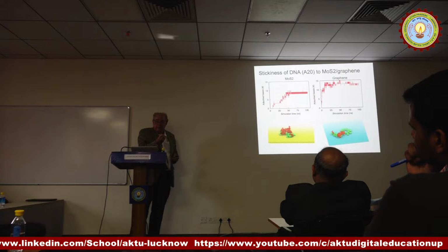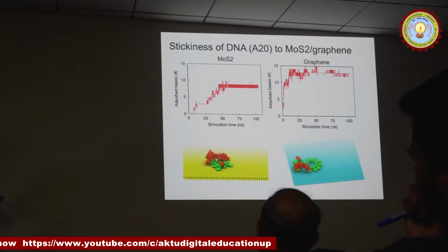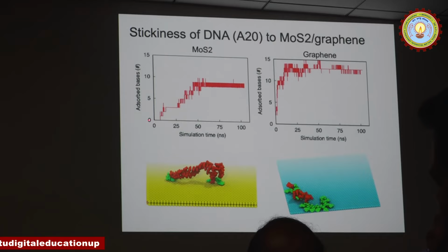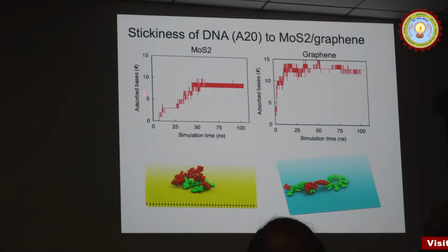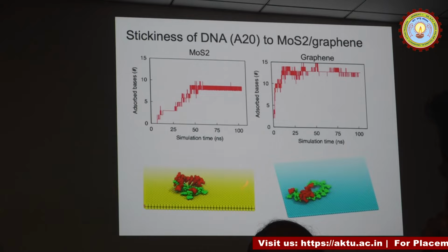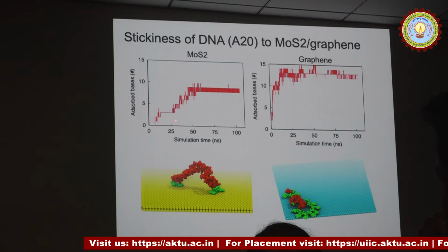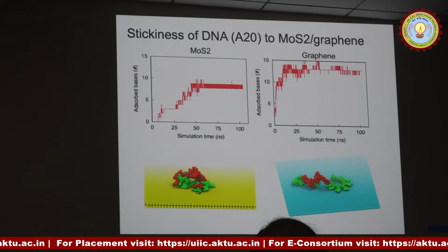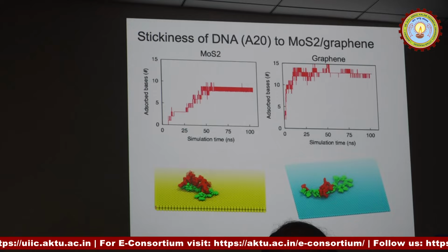So it doesn't go very easily to the pore. Now, MoS2 is actually less sticky. Here is the time it takes for a molecule to stick to MoS2, compared with the time it takes to stick to graphene. And you can see it's much longer than graphene. Graphene is sticking immediately. This is a result of molecular dynamics simulation of a particular kind of DNA molecule on each of these layers.